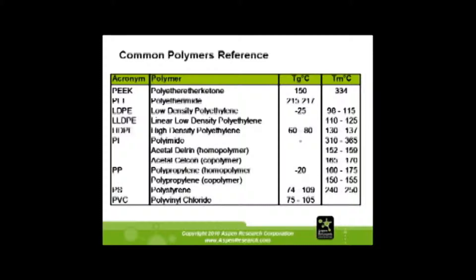Note that the numbers on this slide were corrected. Another sample type we've done a lot is nylons. You can tell the difference by FTIR, but it's much easier to see the difference of 30 degrees on the DSC. Low density, high density, and linear low density polyethylene are also nicely distinguishable — if the materials are not blended. If they're homo-polymers, this is a nice, easy way to tell the difference.